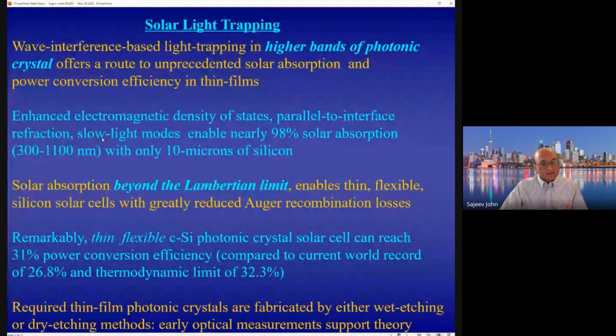Some of the underlying physics is associated with an enhancement of the electromagnetic density of states inside the structure, effects such as parallel to interface refraction, slow light modes, which increase the dwell time of light, which enables 98% of the solar energy over the entire 300 to 1100 nanometer range to be absorbed with only 10 microns of silicon. And what this implies is that with solar absorption beyond the Lambertian limit, it's possible to make solar cells out of silicon much thinner and also flexible.